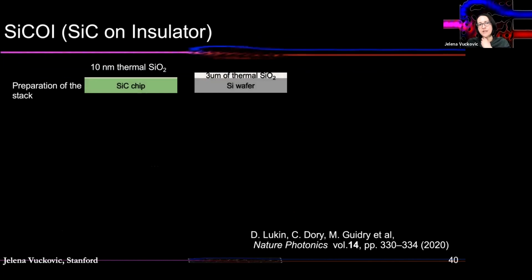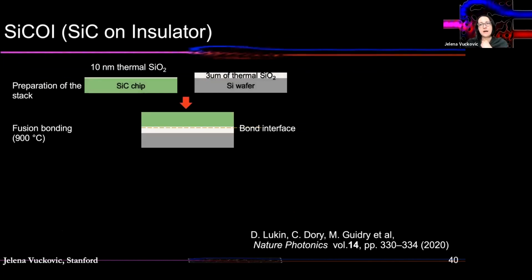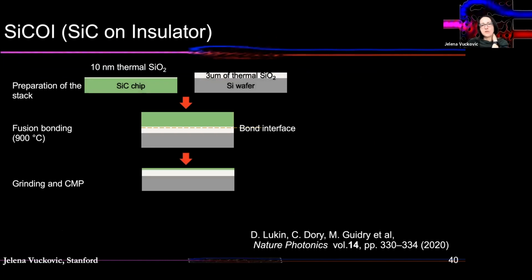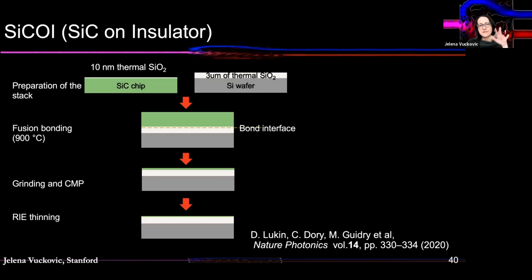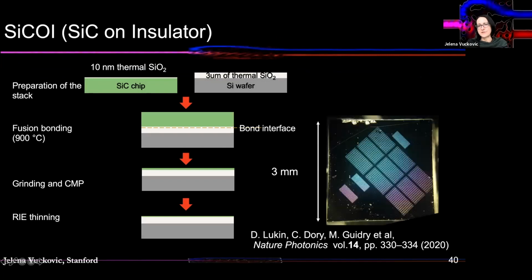So for that reason, since there is no commercially available thin film silicon carbide, we have to develop these thin films of silicon carbide ourselves. And we do that at Stanford. It's pretty simple. We start with bulk wafers, bond them onto oxidized substrates, and then thin them down until we obtain the desired thickness.